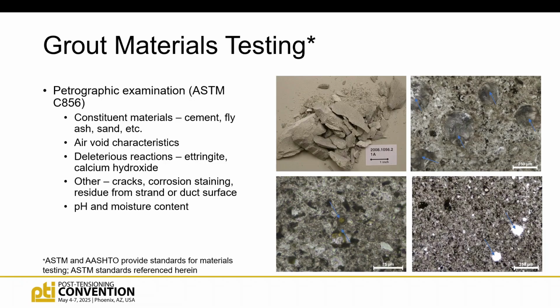So once we've gathered all this data in the field, you will take that back. We have an in-house laboratory where we'll do petrographic examination of the grout. So what does that tell us? It tells us what's in the grout, if it's just cement, if it has fly ash or sand. It'll tell us if it has air void characteristics, if we're interested in that. It'll tell us if it has any kind of deleterious reactions like DEF type things, or excessive gypsum or whatever. It'll tell us if it has cracks or corrosion staining, and it will also measure pH and moisture content.